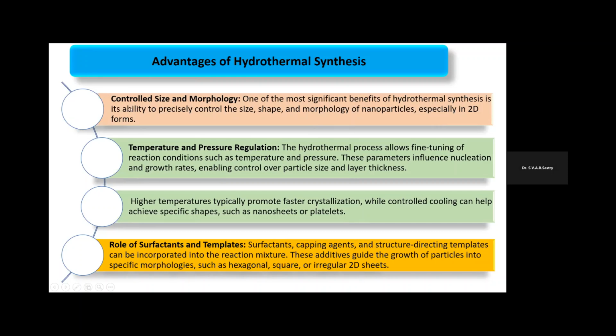We see that it gives controlled size and morphology. Then we have good temperature and pressure regulation. We can fine tune, and accordingly we can get good growth rates of the nanoparticles formed, and also we have control of the size of the particles. Higher temperatures typically promote faster crystallization, while controlled cooling can also help to achieve specific shapes like nanosheets or platelets. So the role of surfactants and templates cannot be underestimated.